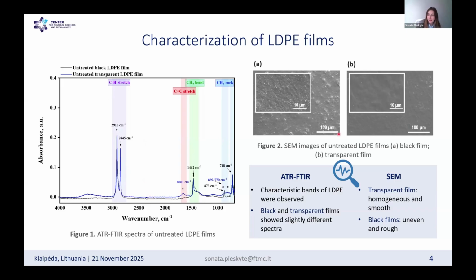And then we also analyzed the surface morphology of both films. As you can see from figure number 2, in part A, there is the black film, and you can see that the surface of the black films was full of irregularities and roughness. Also, we found some flakes, like over here and here. Meanwhile, the transparent films had a quite smooth and flat surface texture, and there were no visible cracks or fractures on the surface at all.